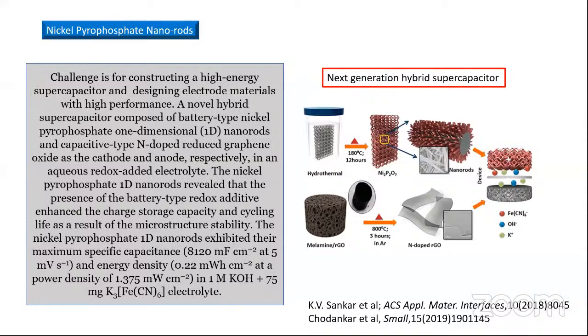And the nickel pyrophosphate one-dimensional nanorods exhibited a maximum specific capacitance of 8120 millifarad per centimeter square at 5 millivolt per second, an energy density of 0.22 milliwatt hour per centimeter square, and the other parameters are given like that. So this is a next generation hybrid supercapacitor, and the synthesis and other devices are very recent ones. One is of 2018, another is of 2019. So very recently, these supercapacitors were devised.